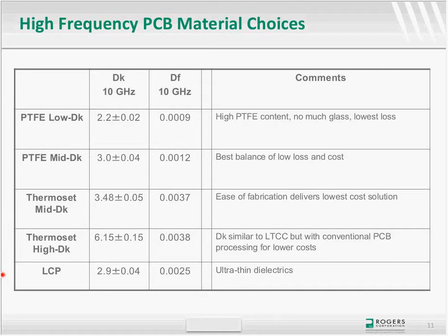But we do find that there's enough individual variation that can happen that we'd rather sit down and talk about whether a particular construction, thickness of the dielectric, thickness of the FR4, or the different layers, may make a difference as well. So it's always difficult to just have general rules. But we do have experience in that, and it can be done, which is typically not recommended in just traditional FR4 multi-layers.